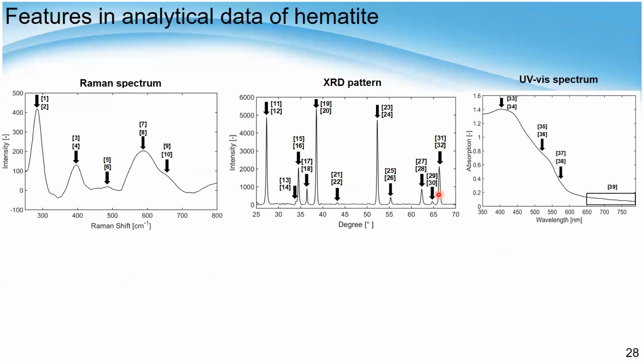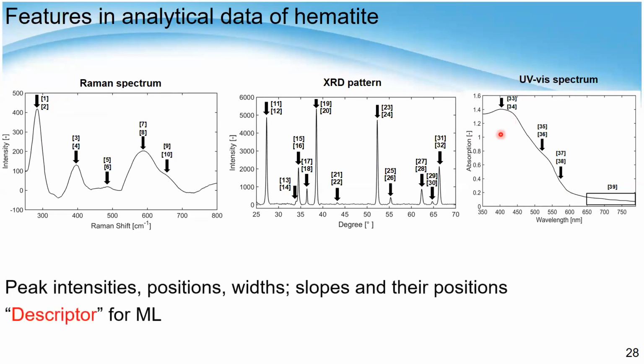We collected these analytical data like the Raman spectrum, which corresponds to the lattice vibration band of the hematite, and the XRD pattern, which indicates the facet of the surface. And the UV-vis spectrum indicates the band gap and also internal transition. So we find the peak intensities and positions, widths, and slopes, and their positions are collected and converted into X values as descriptors for machine learning.